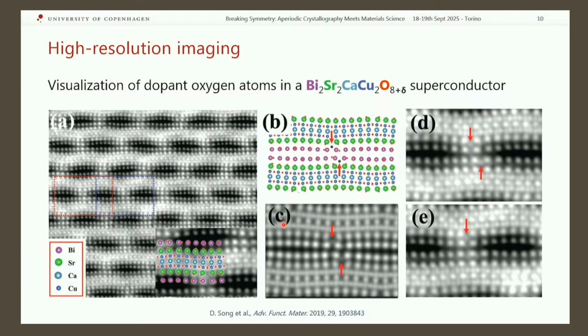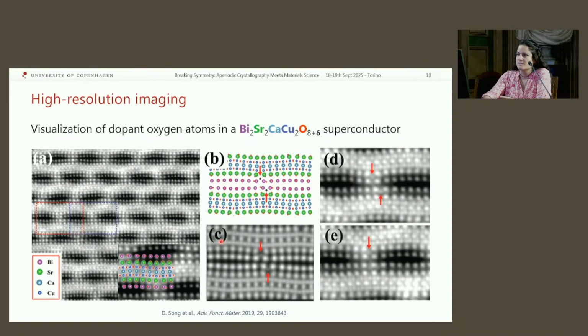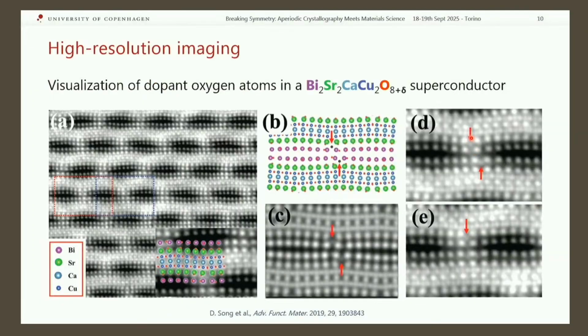And we have said we have an electron microscope, so we can see things. If we magnify enough, and we focus enough, we can actually see the atoms. So this is an example where this very complex oxide has some excess oxygen, which is this delta. So it's a non-stoichiometric compound, and there is some excess oxygen atom that occupies some interstitial site in the structure. So it's clear to see that when there is the oxygen atom, all the other atoms around have to move, shift to accommodate for it.